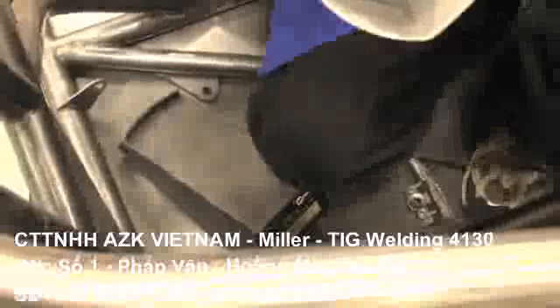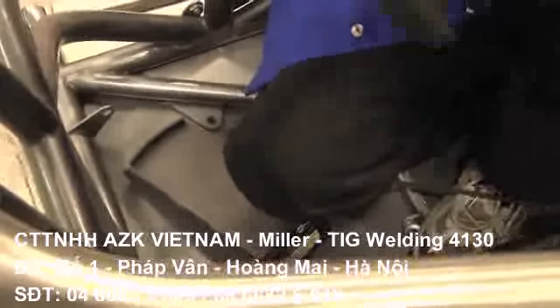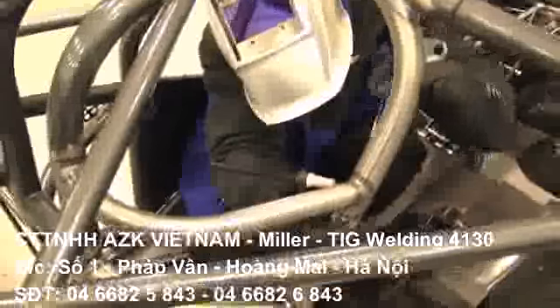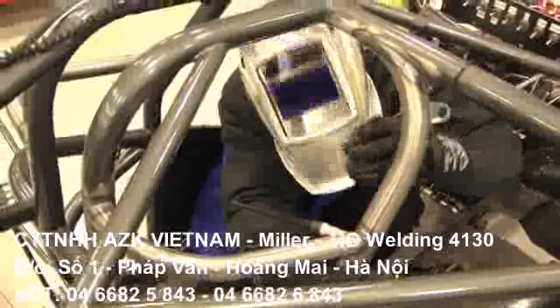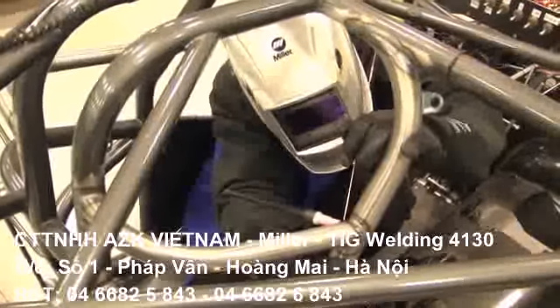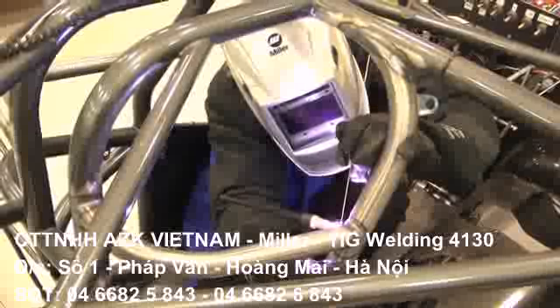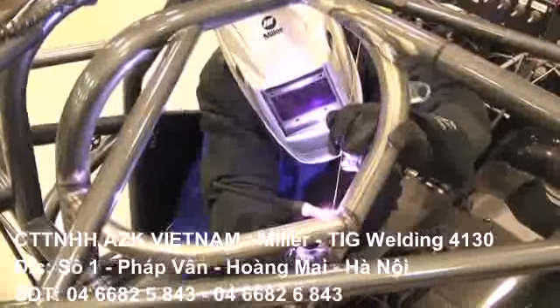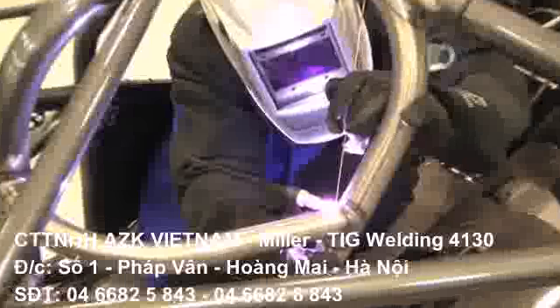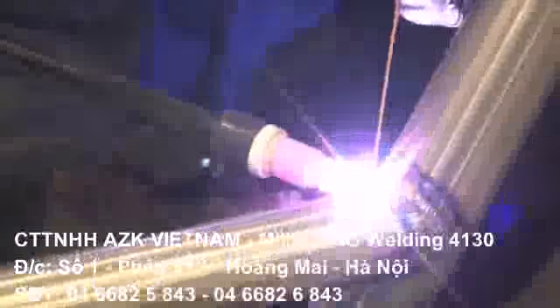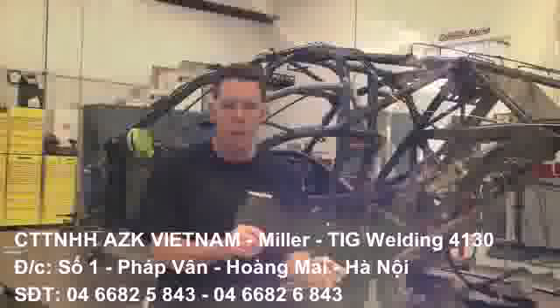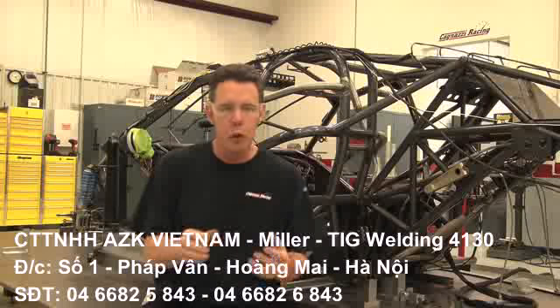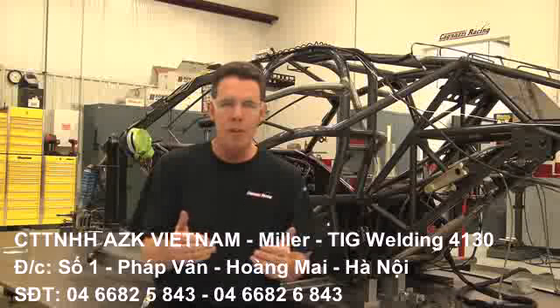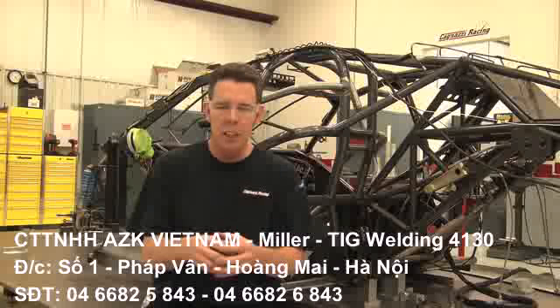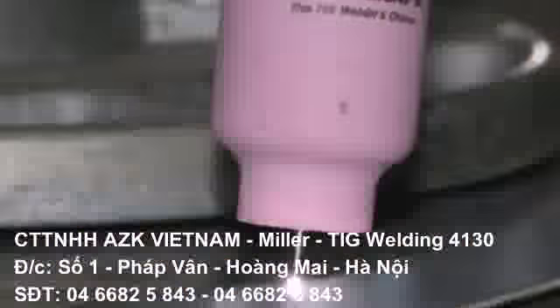The heat's controlled by a foot pedal. Now, there's a general rule of 1 amp per thousandth of material thickness. So let's say I'm welding .065 wall tubing, I'm typically going to be on about 65 amps on my welder. But it's also controlled with a foot pedal that's a rheostat, so like a gas pedal in a car, I can give it more power or less power, which in welding terms would be more heat or less heat. But that's also affected by how fast I weld or how slow I weld. The slower weld at the same amperage setting is going to be a hotter weld because the heat is dissipating into the material we're welding.